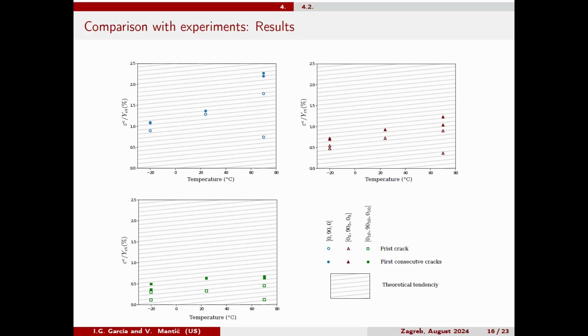So as you can observe, the results are not very good. Let's say that for the thinnest laminate, sometimes you have other kinds of failure like free edge delamination, etc. The tendency qualitatively is okay, but quantitatively we have a lot of scatter. We have a high level of scatter, as you can see. For the medium thickness, we have better results, and for the thickest laminates, we have results that are, let's say, more or less correct. But anyway, they are preliminary experiments, definitely.